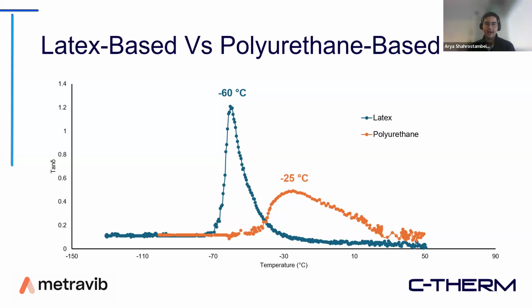So here, the application for condoms using glass transition temperature can be explained in this way: the latex condom shows a glass transition temperature at lower temperatures, which means that at temperatures higher than the glass transition temperature, for example room temperature or human body temperature, around 37 degrees C, the material is softer compared to polyurethane, for example. And the material being softer means that it's more capable of taking the shape.